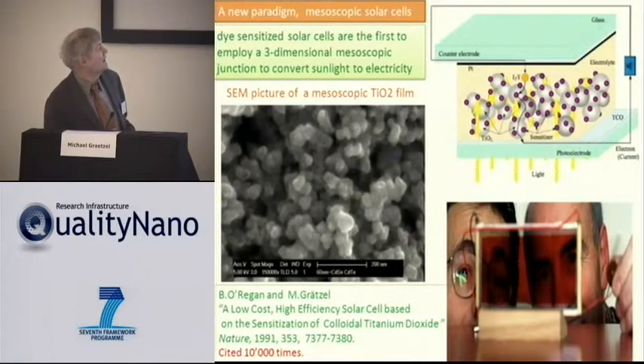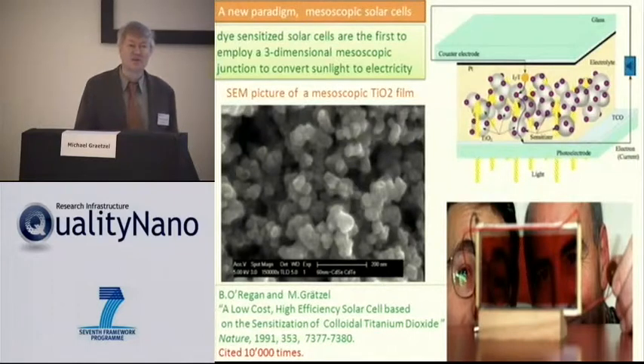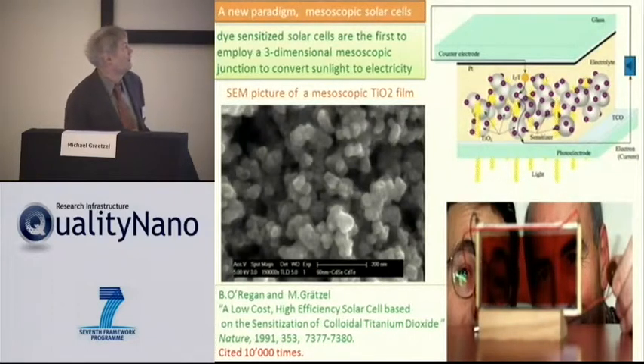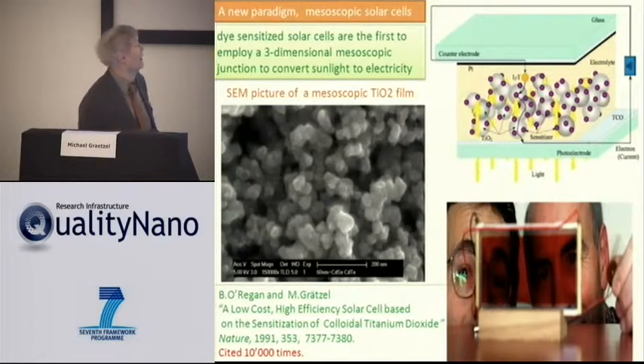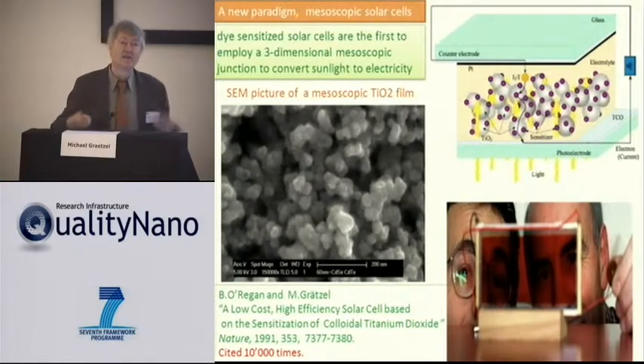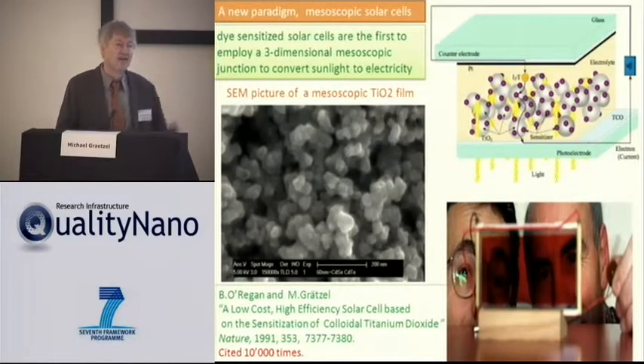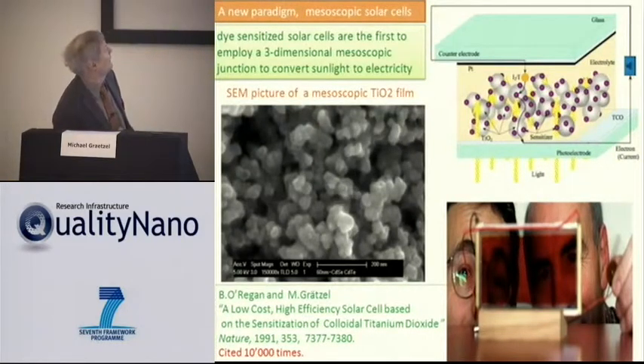And so under light, the titanium dioxide wouldn't do anything. It doesn't absorb any visible light. But we load the film. You see an example of these films here. We just load it with a monolayer of dye. And that is just by a spontaneous self-assembly. The dye is just self-assembled from solution. And then within minutes, you can coat all this huge surface area with a monolayer, a self-limited process. And that's the active part.